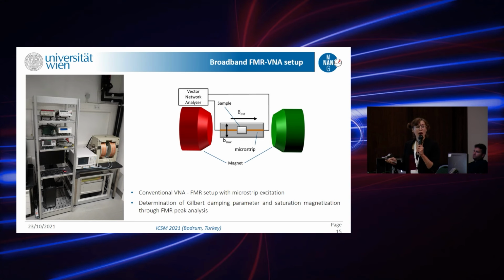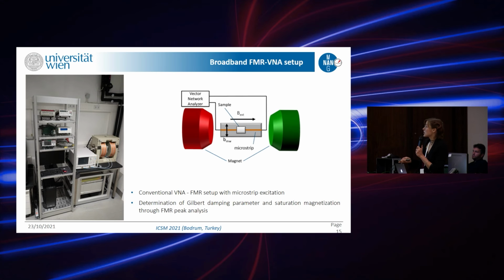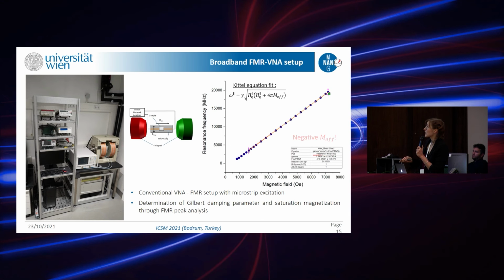So before proceeding to propagating waves, we want to have our Gilbert damping value in this novel material. We also want to have proof that we have out-of-plane magnetization and some anisotropy values. And this was performed on the FMR VNA setup, vector network analyzer ferromagnetic resonance spectroscopy setup, in our lab at the University of Vienna, by measuring and obtaining, for example, a resonance frequency as a function of applied magnetic field.